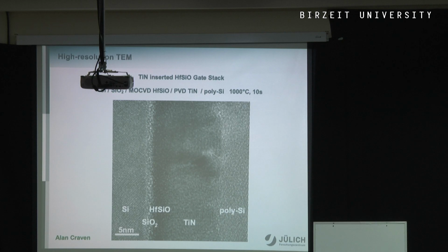As a result of all of these complications, these white features here, which look like atomic scale features, are not necessarily representative of where the atomic columns really are. You have all sorts of multiple scattering diffraction phenomena, and the image approximately tells you which regions of the image are crystalline, which are amorphous, and which are polycrystalline, but it's extremely difficult to interpret.